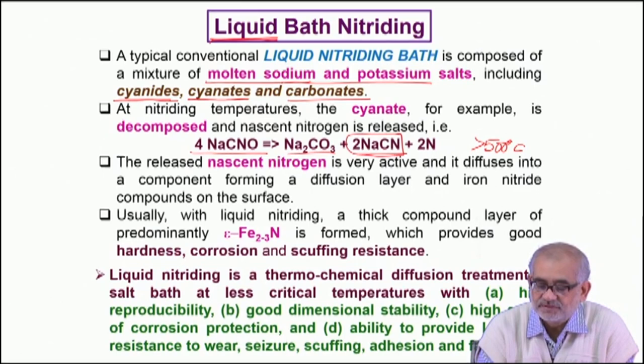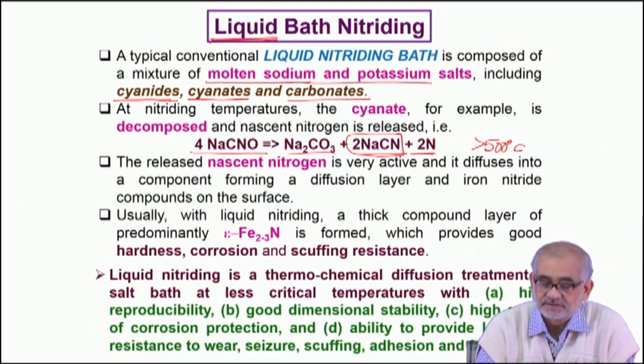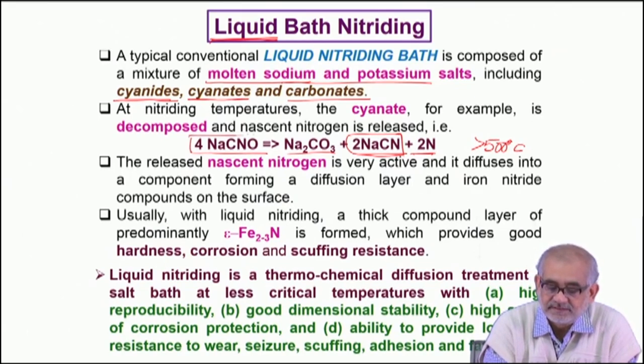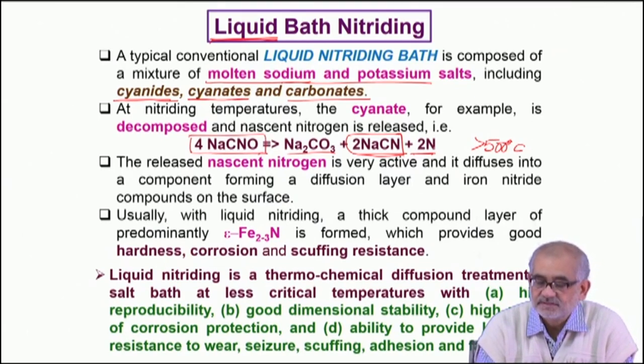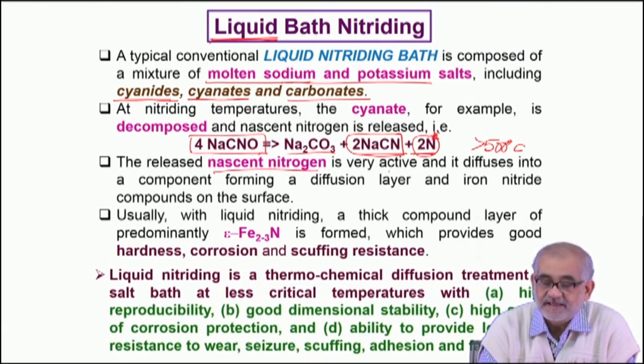This sodium cyanate is very important because in the process we get nitrogen liberated. The bath is called a cyanide bath, and cyanide itself can react with oxygen or other gaseous substances dissolved in the bath and liberate further nitrogen. Having cyanide is what is normally practiced because it liberates nitrogen in nascent form. This nascent nitrogen is very active and can immediately get adsorbed to the surface and then diffuse into the bulk.